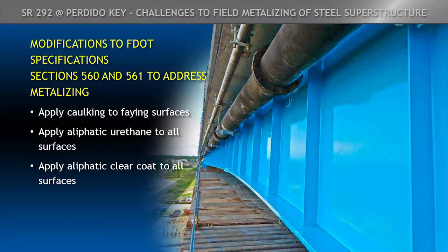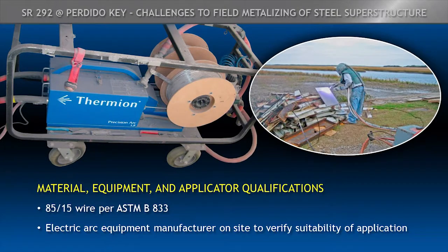And normally with FDOT, we applied the clear coat to only the outside faces sometimes, but we did the clear coat on everything here because of the longevity of the project we were trying to get. This was some of the equipment that we used, but the basic premise here was we had to have the 85/15 wire per ASTM B833, and we also required the electric arc equipment manufacturer on site to verify the suitability of the equipment for the application and to make sure that the applicators were able to use it correctly to produce the specified product.